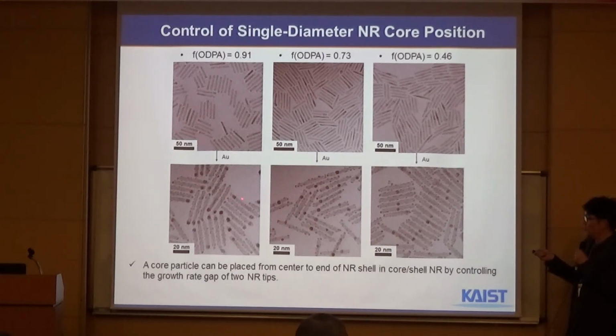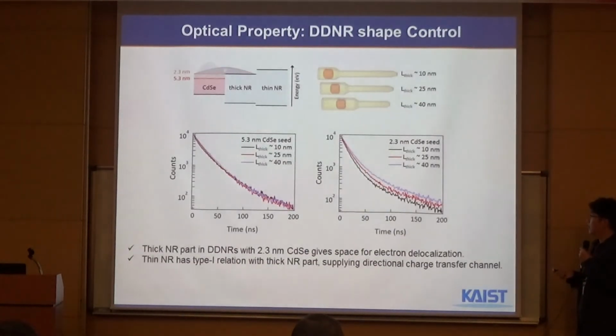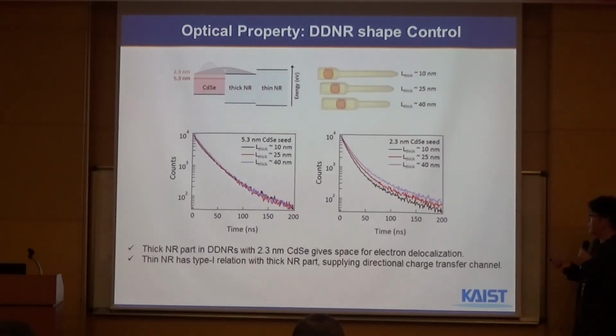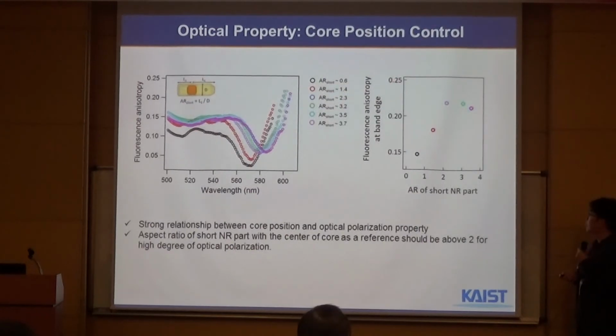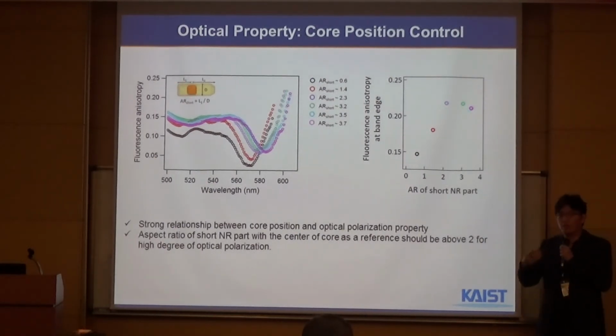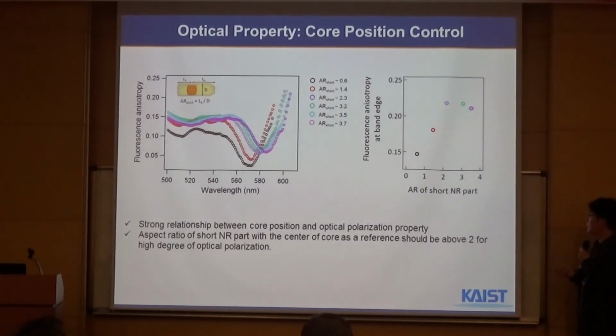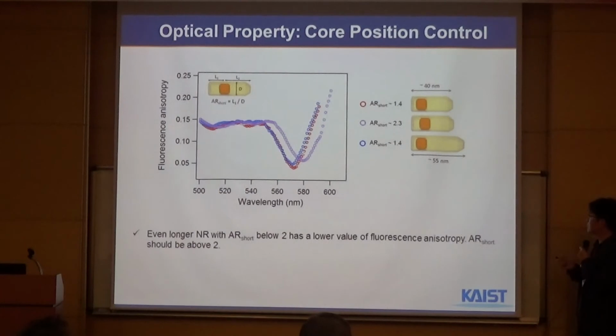For example, in this case, the core is at the tip of the nanorod, and in different cases, you can move this core into the center, the middle of the nanorod. This optical properties data will show you how electron-hole separation is controlled by changing the nanorod dimensions. Some of the polarization study data show that the nanorod dimensions, especially the short aspect ratio part here, is going to affect the nanorod polarization properties a lot more than other cases.